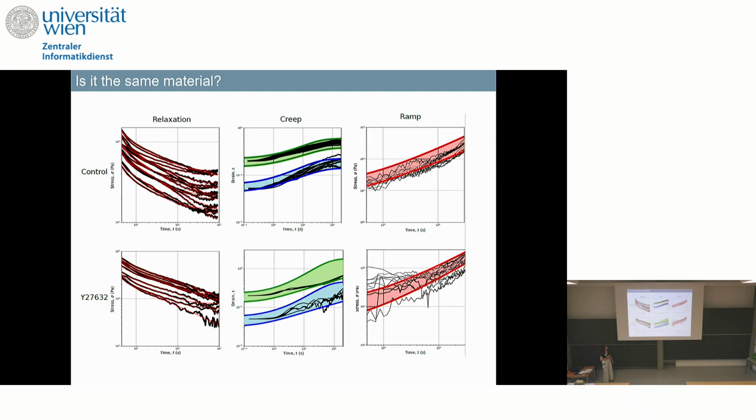we can see that their creep response is different. So it does take more time. So we didn't really see a plateau at the same level. But we did see what looked like an inflection. These data are a bit more noisy because the monolayers are a bit more, let's say, variable. And with the same parameters, we did extract the ramp response as well. And we did have a good agreement for biological data.